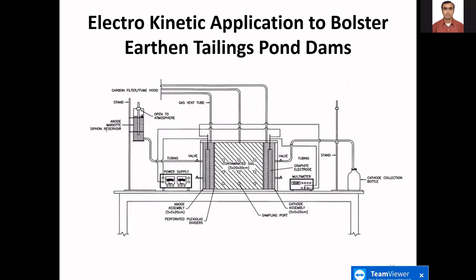This is one of Krishna's electrokinetic testing cells. The central portion here is where the tailing sample was located, was subjected to treatment. We've got the graphite rods within water-filled reservoirs. This provides for water cooling to a certain extent, but what it does more than anything else is that it lowers the amount of current that can be transmitted from the anode to the cathode. The water prevents the system from heating up because it minimizes the contact of the solid electrodes to the solids in the clays. So it minimizes the power demand, if you will.